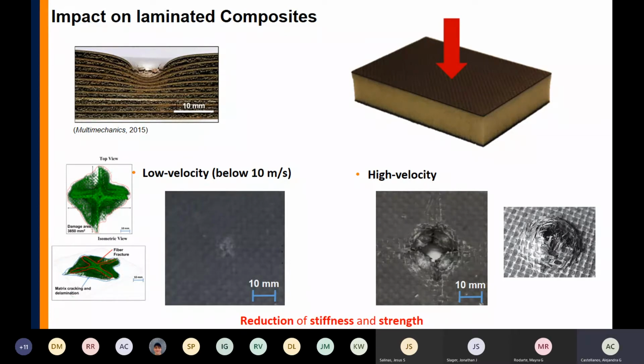However, the challenge that we have in composites is the low velocity impact. Because on the surface, as you can see in this picture over here, the surface doesn't have any damage, but that doesn't mean that inside your composite you're not going to have damage. These are micro CT pictures that show the damage inside your composite. The problem with low velocity impact is that it produces damage that you don't know is there, and the structure can fail catastrophically.